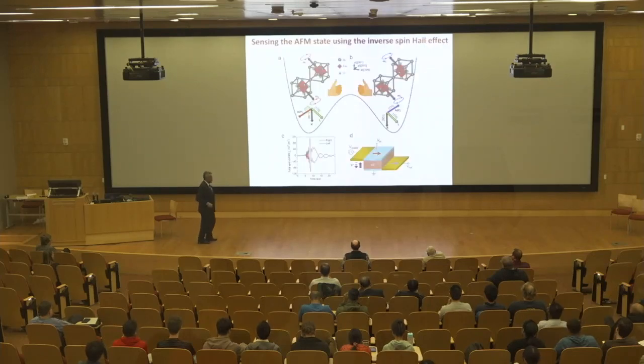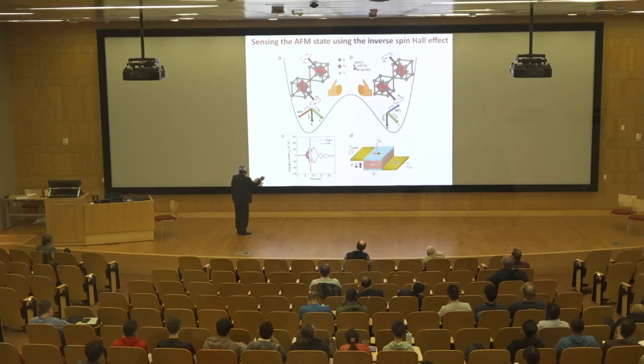So the experiments, this is still unpublished because we're haggling with a bunch of referees. And you have the ferroelectric multiferroic material. It has the polarization, which is shown by the red arrow. You switch it, it goes that way. Our hypothesis was that the magnetism, the antiferromagnetism, also changes, and it does. And therefore, the spin current, total spin current, also changes from positive to negative as I switch my polarization state.